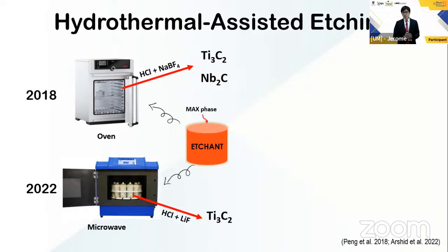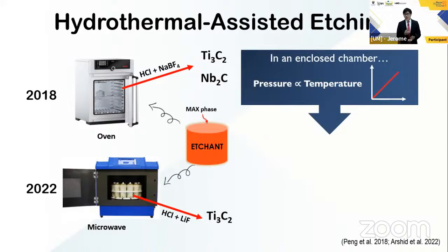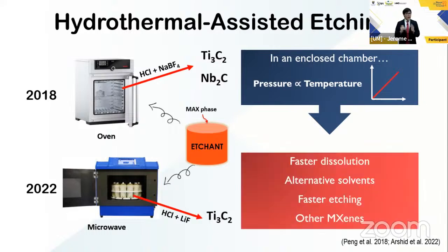Both of these approaches completed exfoliation in less than 20 hours, which is a marked reduction compared to the conventional methods, which require 24 hours. Because in an enclosed chamber, as the temperature rises, the pressure increases as well. And this aids in the dissolution of fluoride salt in aqueous dispersion, enhancing the etching efficiency of weaker etchants.